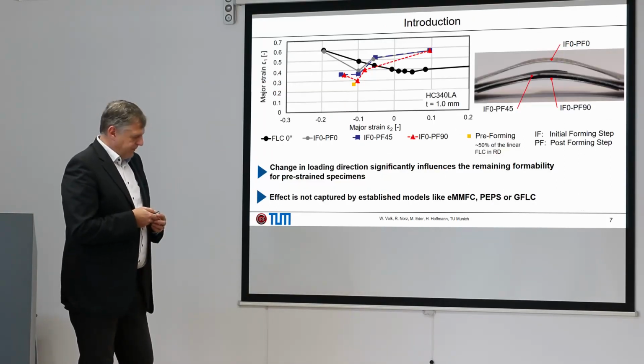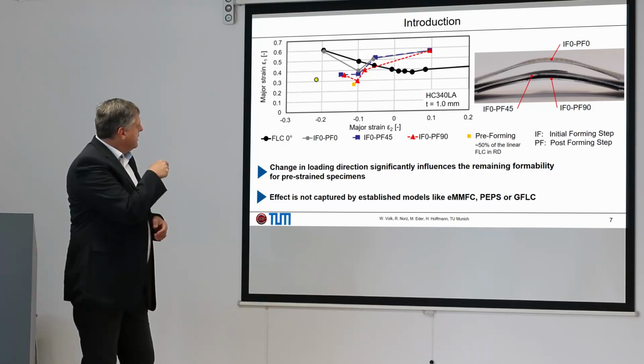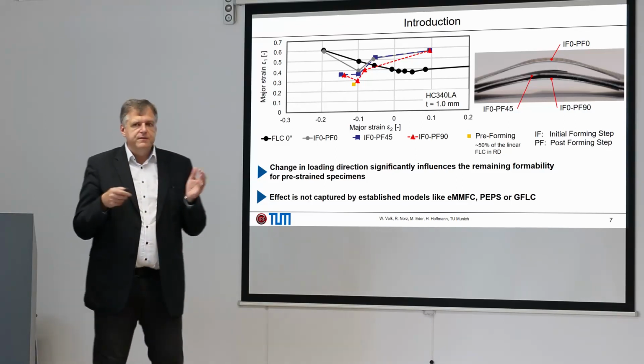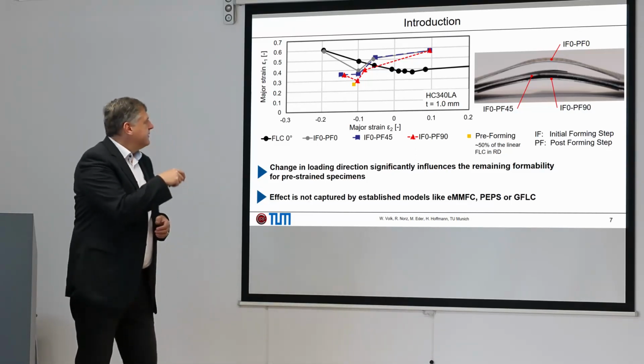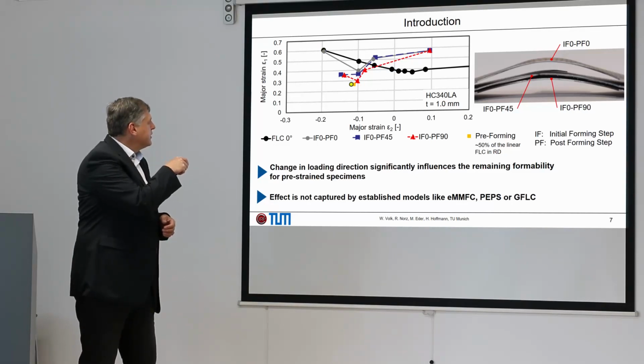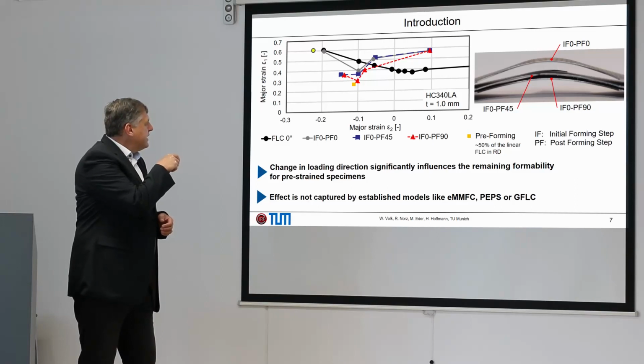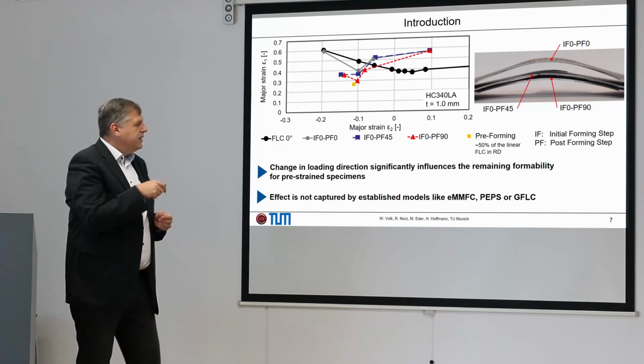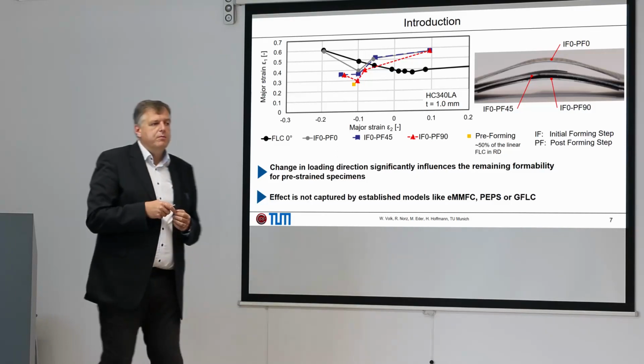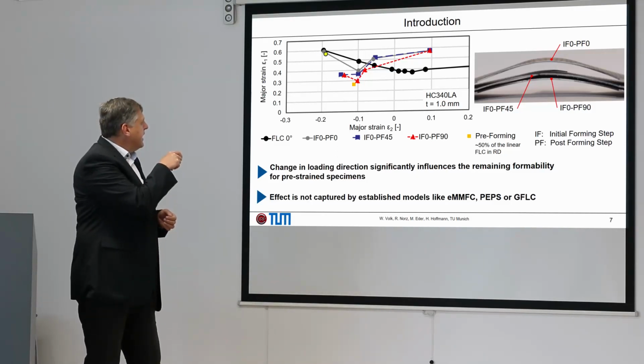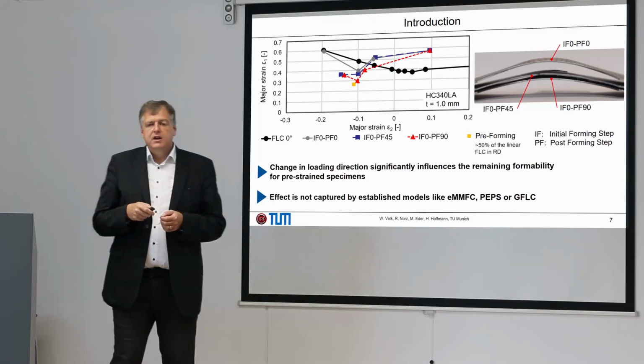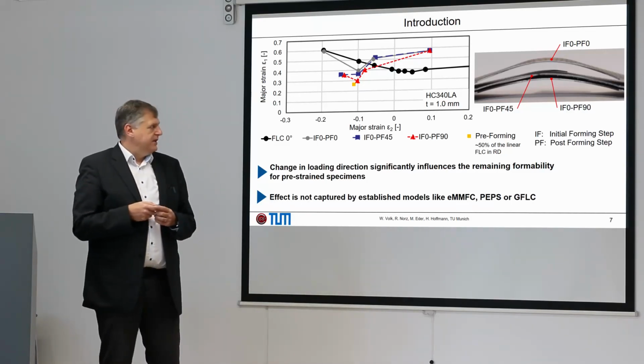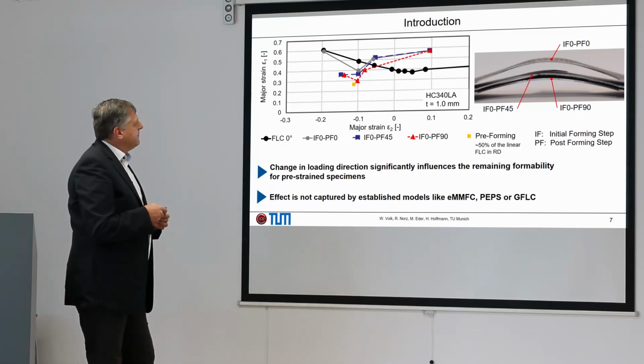Please have a look here. So here in our strain diagram, this is the initial forming step of around 50% of the FLC in uniaxial direction. And with the gray curve, where it's 0-0 combination, we have the well-known material behavior. Here, absolutely clear, no difference. And then when changing in plane strain, we reduce formability, and when we go to biaxial strain, we are winning formability. But now have a look for 45 and 90 degrees.